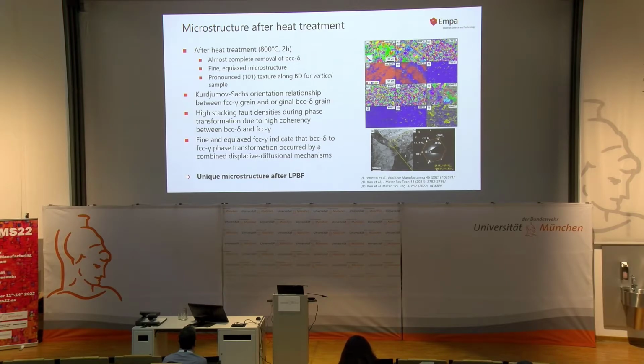And with that, we maintained also the texture: from the 001, we can get a 101. And this is what we found out because we have really a close orientation relationship between these two orientations in FCC and BCC, as we found out.